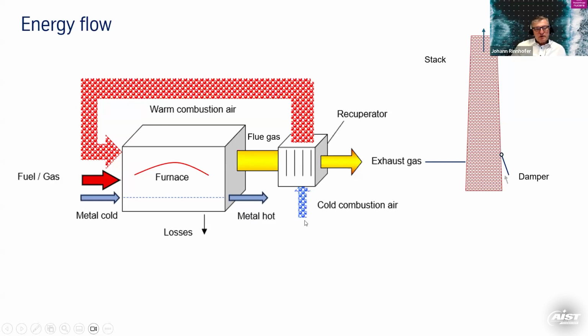There are also different concepts of air preheating. So we have this recuperator as it is shown here. So we take the hot gases from the furnace, go through a recuperator and preheat the cold air, which is going to the burners in a warm state, say at 400 to 600 degrees approximately.